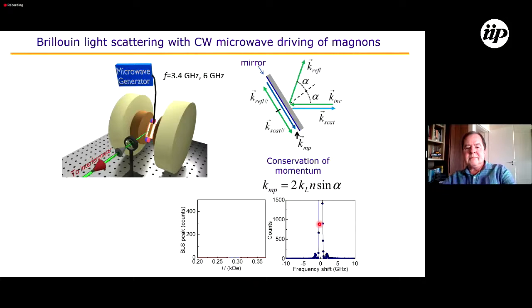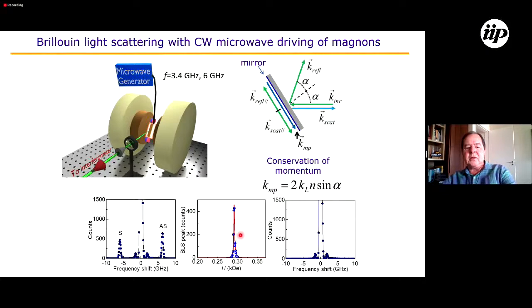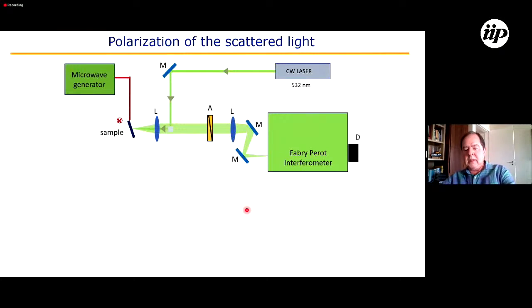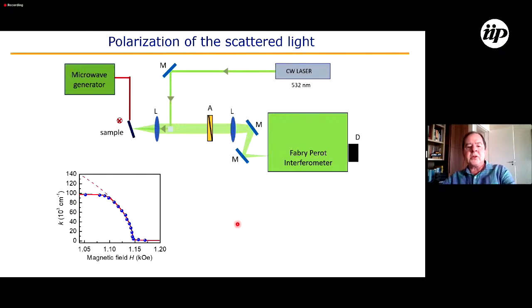So by changing the magnetic field, we see Stokes and anti-Stokes scattering, and this shows up only at this value of the magnetic field that corresponds to the excited wave number given alpha. So we ask, what is the polarization of the scattered light? The measurement that I showed, the magnetic field versus angle, gives this plot here.